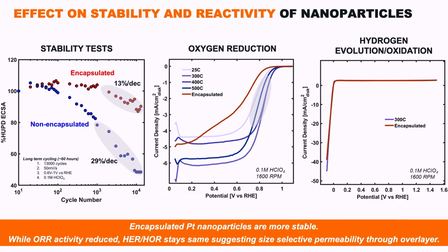And so how does it change the stability and reactivity of the supported platinum nanoparticles towards fuel cell and electrolyzer reactions like oxygen reduction or hydrogen evolution oxidation? So firstly, talking about stability, we looked at the hydrogen under potential deposition area, which is this y-axis, as a function of the cycle number, and we saw that for the encapsulated catalyst, the reduction in the accessible surface area was lesser compared to the non-encapsulated, suggesting that the overlayer is kind of fixing or immobilizing the platinum nanoparticles on the support, thereby improving stability, preventing dissolution or agglomeration under EChem conditions.